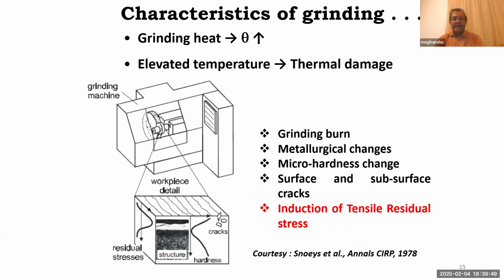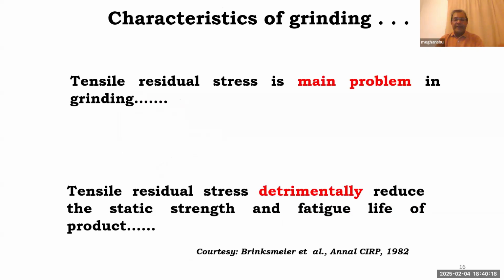This elevated temperature condition or grinding heat will induce grinding burn. It will also result in metallurgical changes, micro hardness variation, surface and subsurface cracks, as well as this large amount of heat will introduce tensile residual stress in the workpiece component or the manufactured product. This tensile residual stress is detrimental. According to literature or according to the research outcome of various scientists, tensile residual stress is the main problem in grinding, and that is not desirable by any customer. This tensile residual stress detrimentally reduces the static strength and fatigue life of the product.